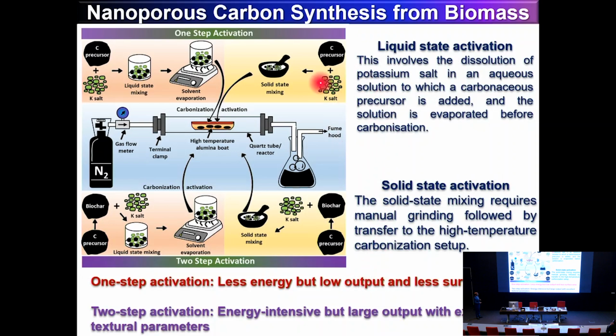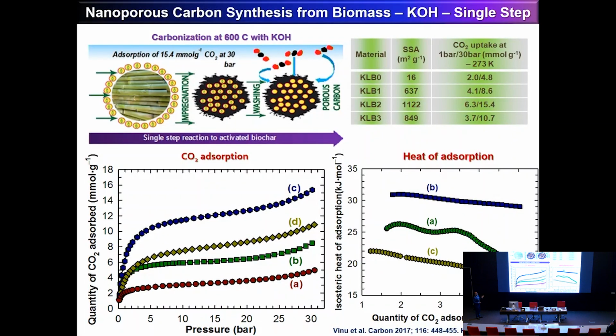First, we heat the material at 500 degrees centigrade and mix, with the salt added, and then at 600 or 700 degrees centigrade, and remove the salt with hot water, and you will get very high surface area carbon. And this is a single-step activation, which is what people normally use. The surface area is quite less. The CO2 absorption capacity is almost 16 millimole, which is very low.